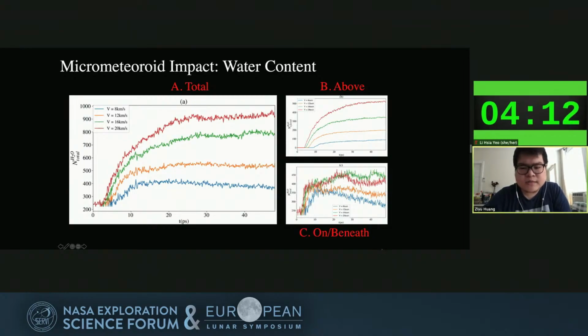the impact site is strongly related to the velocity. So for 8 km per second, you can see the abundance of water molecules almost goes back to the original abundance. But for 20 km per second, the impact almost doubles the water abundance. And for those above the surface, they're classified as molecules ejected from the surface. And almost 50% of them escape from the Moon, and 50% of them contribute to the exosphere, or they are redistributed to the ground.